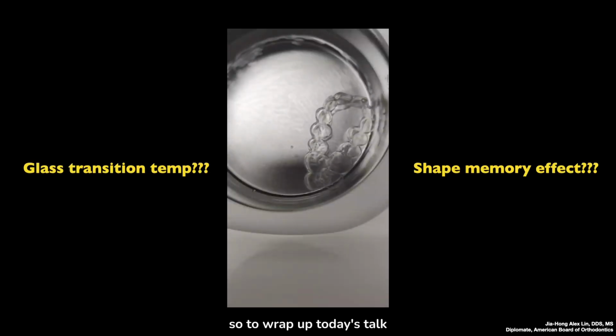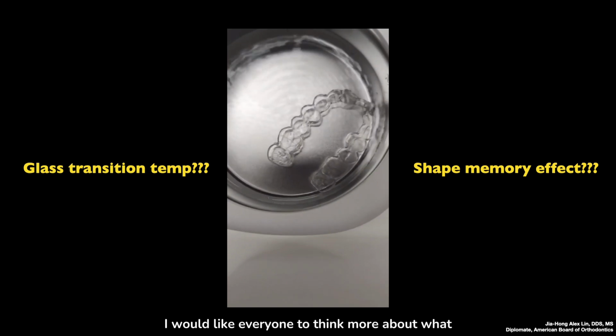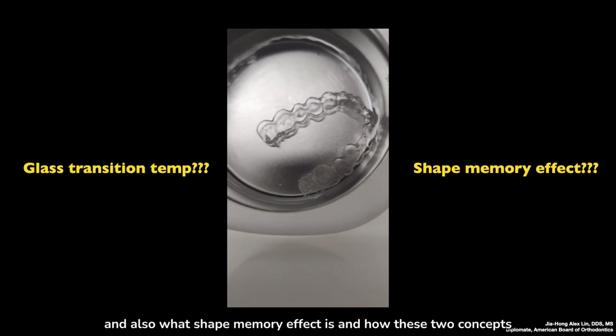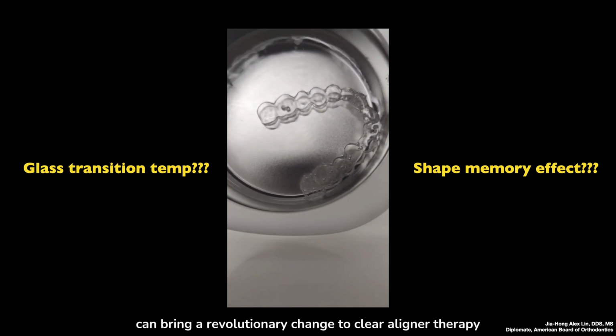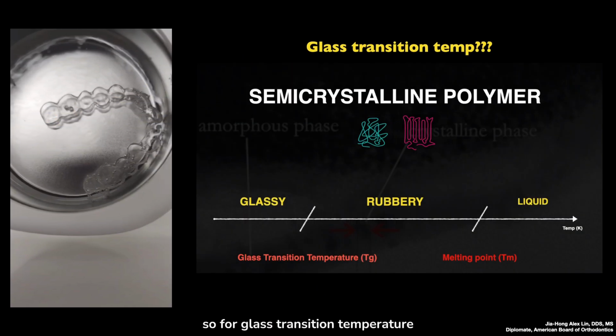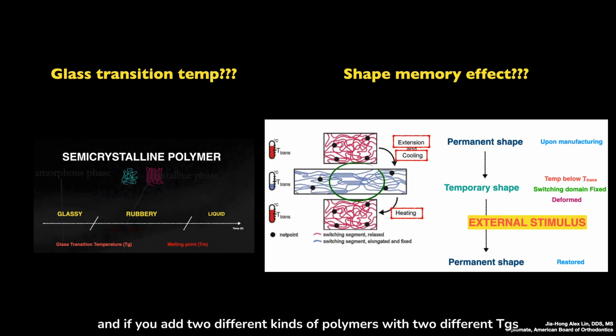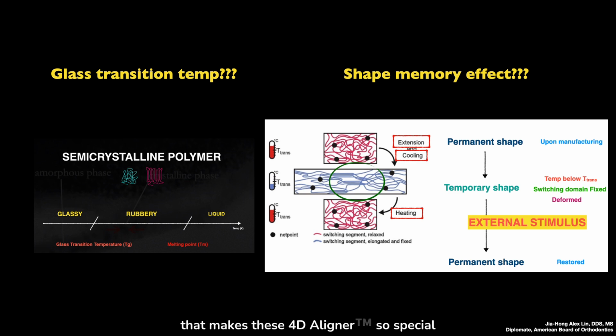So to wrap up today's talk, I would like everyone to think more about what glass transition temperature means, and also what shape memory effect is, and how these two concepts can bring a revolutionary change to clear aligner therapy. So for glass transition temperature, all you need to remember is that the amorphous part of polymers goes through softening after reaching their TG. And if you add two different kinds of polymers with two different TGs, and you go above or below the TG of the switching segments, this allows you to see the shape memory effect